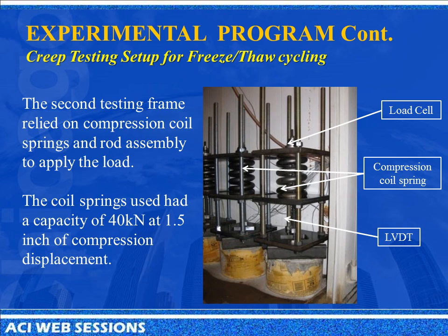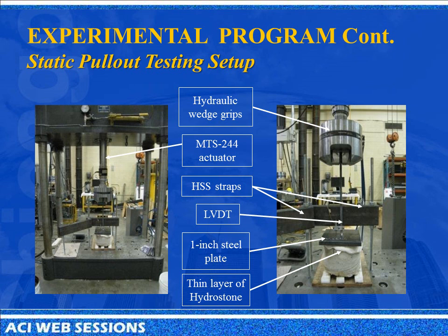The second testing setup, which was for the freeze-thaw, and like I said before, it had to be put into an environmental chamber for the freeze-thaw cycling, so it has to be less in space. So we actually used the setup that's commonly used, which uses compression coil springs with a rod assembly. A compression coil spring that we use had a capacity of 40 kilonewtons at 1.5 inches of compression displacement, like shown in the picture. And each setup had a load cell to monitor that load during the period of the testing.